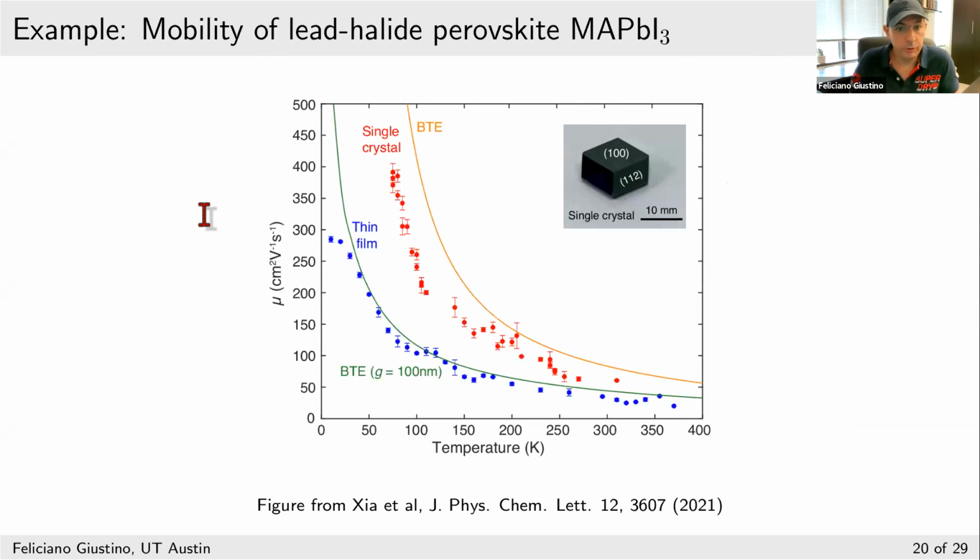So we will have a lecture on polarons on Thursday. Actually, I will give you a slide about the strength of the electron-phonon coupling in MAPI in the second lecture. Basically what we know is that the polaronic mass enhancement in MAPI is of the order of maybe 20 to 30%. So it's not gigantic. It's similar to other semiconductors. So when people refer to polaronic effects, they are mostly referring to rotations of the cations. That's a little bit trickier because it involves anharmonic effects. But those effects should not be important in this temperature range. I hope that answers the question.